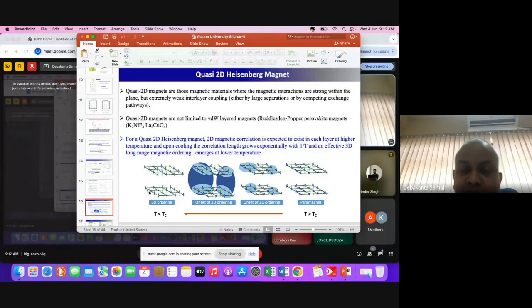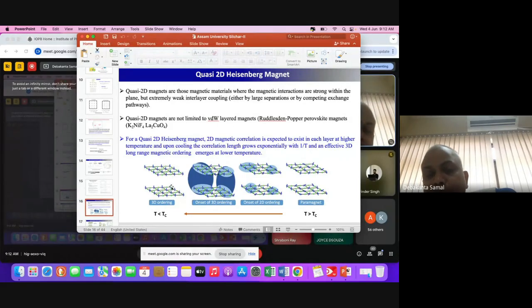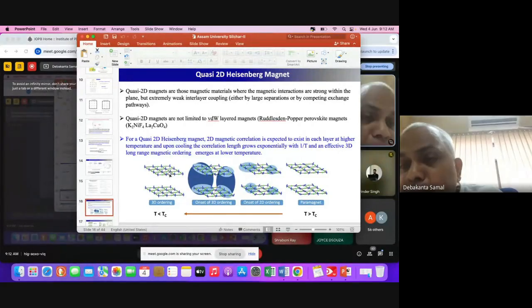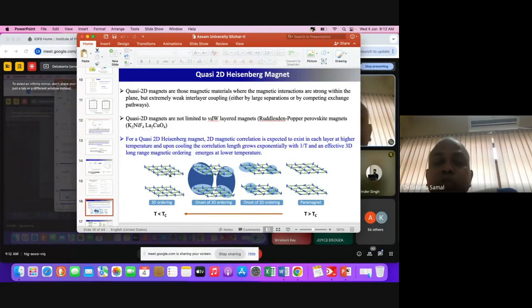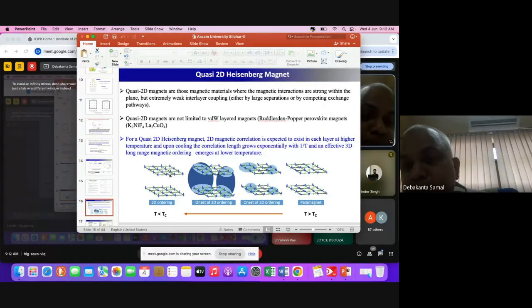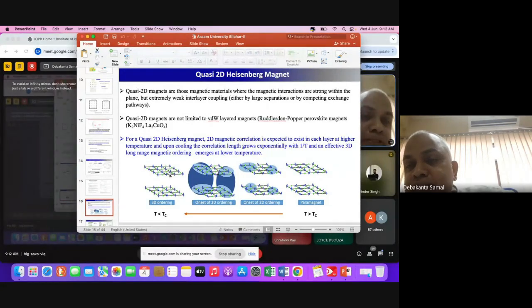So here what you find is a strong exchange interaction in the plane, which we call intraplane. But if you compare the exchange interaction between two layers, that is very weak. That means the intraplane exchange interaction is much, much larger than the interplane exchange interaction. These are known as quasi 2D magnets. In my previous slide I showed you a pure single layer, where they are talking about the Mermin-Wagner theorem. Now what I'm talking about is not one layer. There are many layers, but they have very weak coupling between them. This kind of system is a quasi 2D Heisenberg magnet.